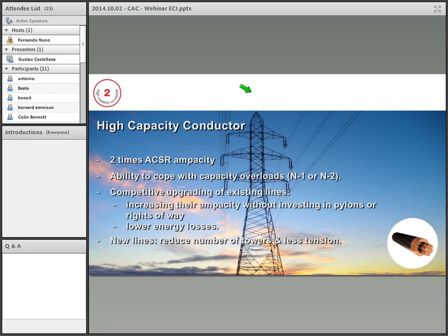And that's really important for the sector, because without the need of investing in pylons or reinforcing the towers, they can transport double power, double energy. And that's as well really good because it has the ability to cope with N-1 or N-2 situations. N-1 means that if one line falls down, then the line that you design has to have the possibility to transport the energy that was on the line that has fallen down. So this is a really interesting solution for the sector. So it's competitive for upgrading existing lines, and as well, we are doing that with low energy losses.